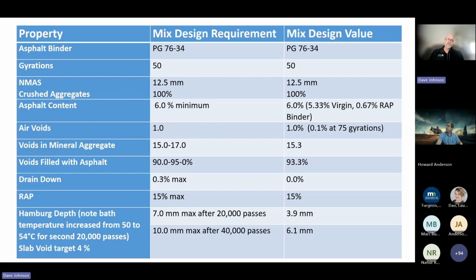And the other thing that's worth noting is normally with your Hamburg and other performance tests, you typically target a 7% air void value on those specimens. Because they were designing to lower air voids and going to be requiring a minimum of 96% density in the field, the decision was made to also make an adjustment to the Hamburg slabs. And we can see that that target was 4%.